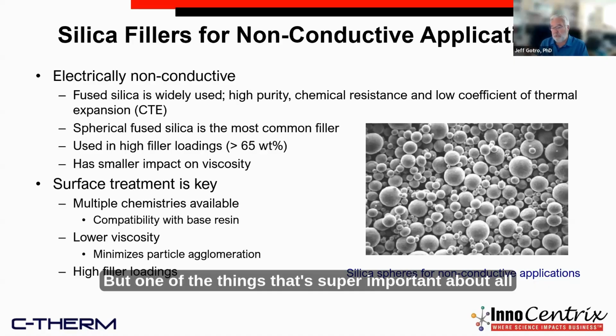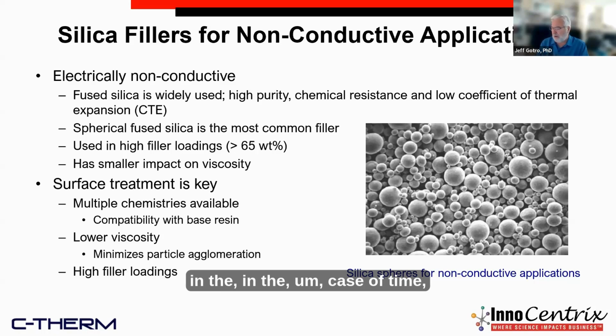But one of the things that's super important about all these fillers, and I didn't touch on it in the interest of time, is that surface treatment is key. So the silvers are surface treated, and now the silicas are surface treated. Multiple chemistries are available, and these allow you to control rheology, and they also couple the resin to the filler. And then you can treat the fillers so they don't agglomerate. Because remember, Arya was talking about agglomeration. That's a bad thing. So you can surface coat these fillers so that they don't agglomerate.